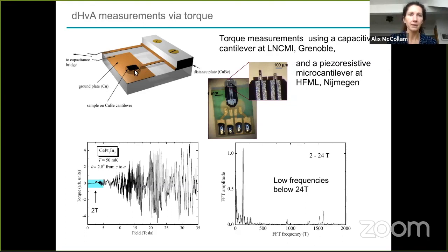The experimental technique is that you put your sample on a cantilever. The magnetization of the sample, so M cross B, is the torque, and as you change the magnetic field, the magnetization changes, your torque changes. In this case, the capacitance between the lever and the bottom plate would change, and in this case, the lever flexes, and the resistance of the legs of this lever will increase or decrease as the lever goes up and down. So they both give us rather sensitive measures of the torque.